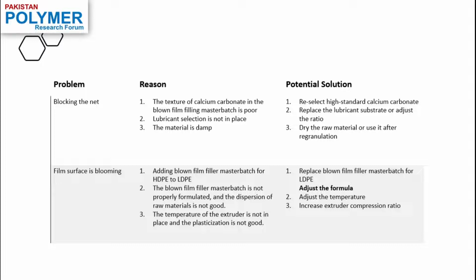And another reason can be that you're not properly formulating your master batch, and the dispersion of the raw material isn't good because of the formulation that you're using. Or the third reason can be that the temperature of the extruder is not in place, because you might be using the temperatures that you were using for making an LDPE master batch for your HDPE master batch. There's a difference between the melting points of both the resins. HDPE melts at a higher temperature as compared to the LDPE. So if you're using the same temperatures for both the materials, you're going to get the problem of mixing and dispersion and blooming on the